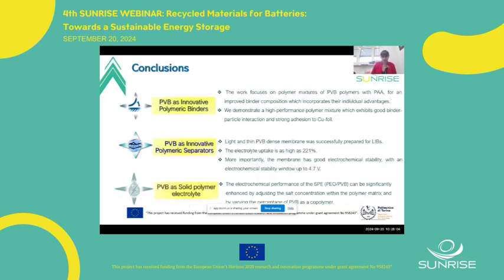So as a conclusion, we tried to use PVB as binder, separator, and solid polymer electrolyte. The result for binder is that the mixture of PAA/PVB 80-20% is the best composition, showing enhanced rate performance and initial Coulombic efficiency, good for both lithium and sodium-ion batteries.